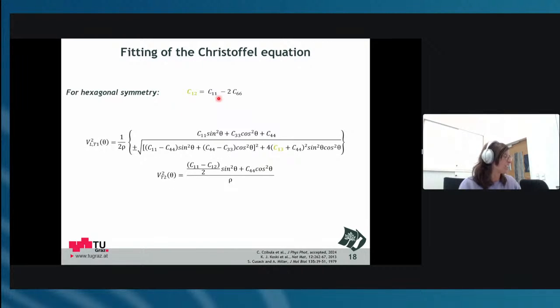The next three are not so nice. They come from the Christoffel equation. For C13, you need to fit this formula. These formulas give you the sound velocity of the longitudinal wave, the first transverse wave, and the second transverse wave at all angles of orientation. It's very nice. You need a few data points for that, which is why I did these other measurements. And as you can see here, the longitudinal and the first transverse wave are in a certain relationship to each other, because the formulas differ just by this plus and minus.